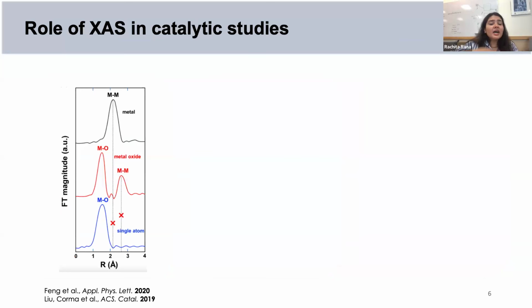So with that, I want to point out some of the bigger challenges that the atomically dispersed catalysts face. One of the key results that you would see when you use X-ray absorption spectroscopy in atomically dispersed catalytic materials is this, what you see in black here, where the absence of a metal-metal bond or scattering path is indicative of having an atomically dispersed catalyst.